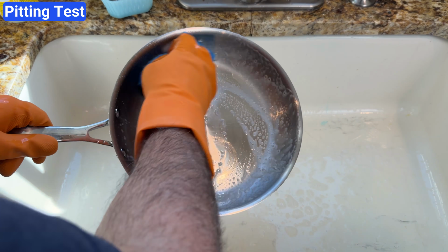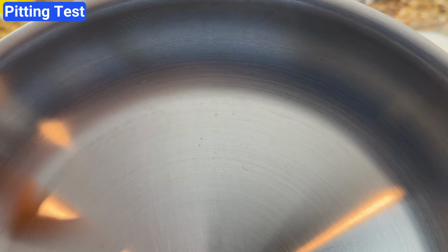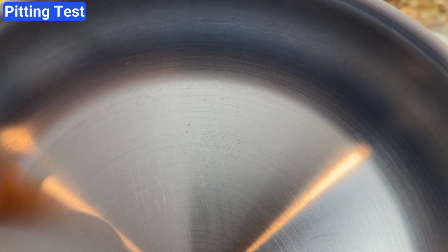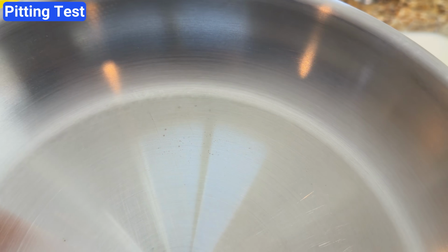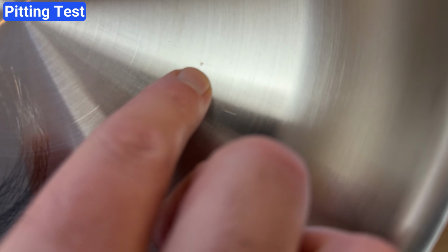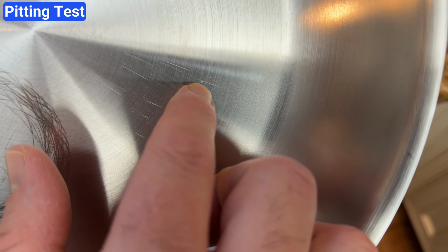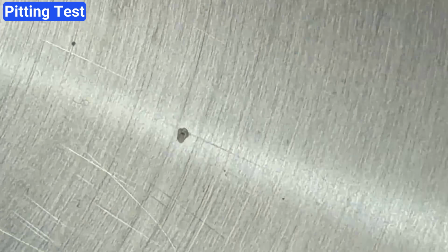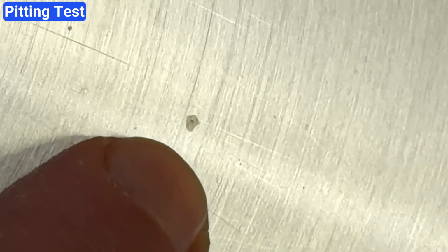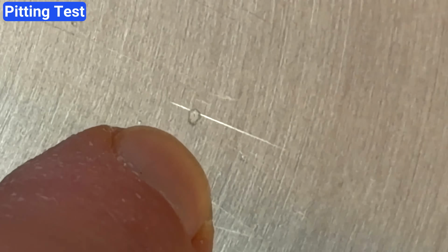The stainless steel pan had small dark spots starting to form, and at first I just thought this might be mineral buildup, so I cleaned it with vinegar and Barkeeper's Friend. But the spots didn't come off. They hadn't corroded through the surface yet, but it was the beginning of pitting. After the second and third rounds, more spots appeared on the stainless steel pan, and when I zoomed in, I could see that they were actually starting to eat into the steel. When I rubbed them with my fingernail, I could feel the indentation. The titanium pans didn't show any signs of pitting.